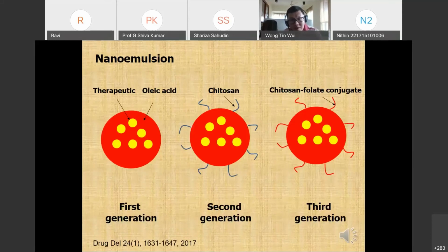Now, so far for the solid chitosan nanoparticle, we also designed liquid nanoemulsions for inhalational studies. In this study, we prepared first, second, and third generation nanoemulsions. The first generation is very simple: basically, oleic acid, a lipid component, for us to prepare an oil-in-water nanoemulsion. In the second generation, we have chitosan decorated on the surfaces of the oil droplets. And in the third generation, we have chitosan-folate conjugate decorated on the surfaces of the oil droplets.